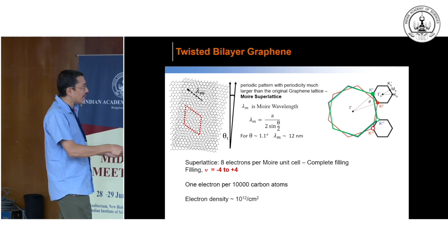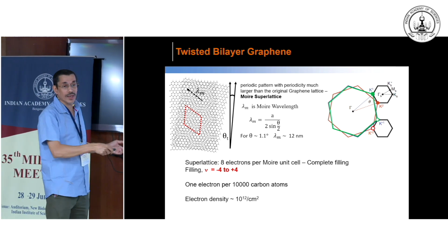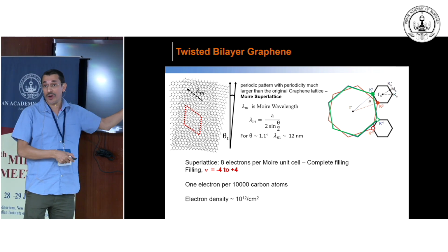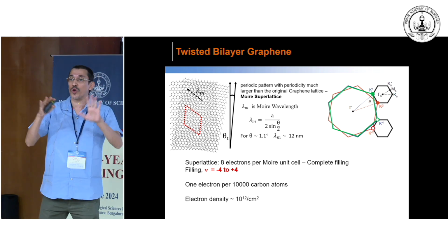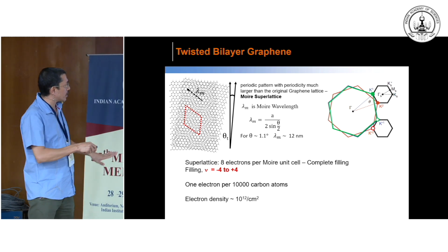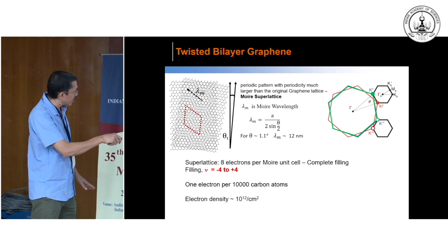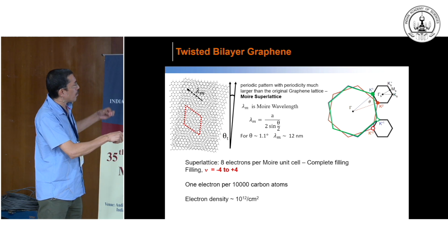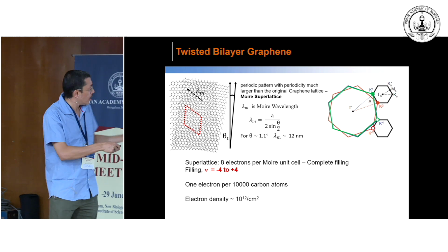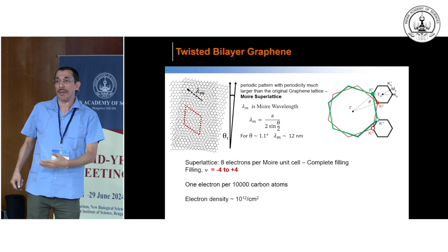And this 8 electrons come because you have 2 spin, plus there is a valley degree of freedom in this case, and there are 2 layers, so that gives you a total 8 degeneracy in the system. So the point is, in this real space unit cell, if you fill by 4 electrons, you completely fill the band, or if you remove the 4 electrons, you completely empty the band. So remember,